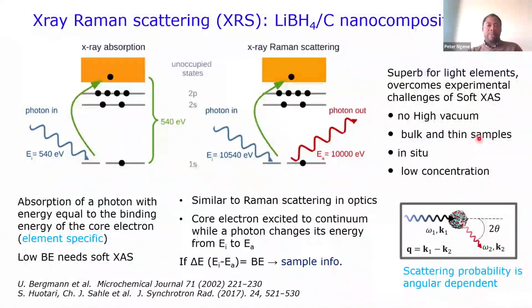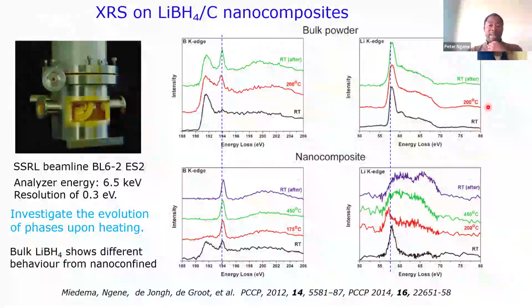Both bulk and thin samples are quite good, and we can also do in situ, because we can now flow gases in that. And we can also go to lower concentration. Of course, low is quite relative. So the first experiment that we did was with Peter Miedema, who was my colleague then.